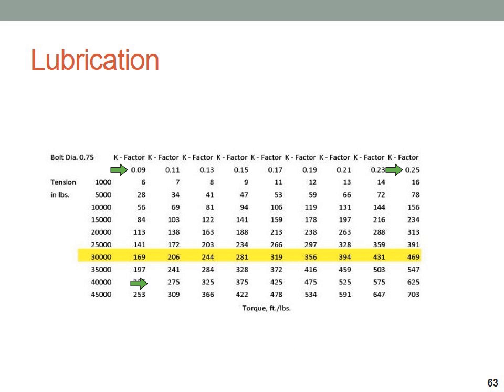If we apply that math to reach minimum tension on a 3/4 inch bolt, let's say it's a Dacromet coated assembly with a supplemental lubricant, which tends to be very slippery, I actually by hand could reach minimum tension with a spud wrench on a 3/4 inch bolt with a very low K factor or an effective lubricant. But it also could take as much as 470 foot-pounds to reach the same tension with a dry bolt, nut and washer. So it's really impossible. This is why we worry so much about torque in this industry and how variable it might be; any of those are possible with any given fastener assembly depending on the condition that it's in.